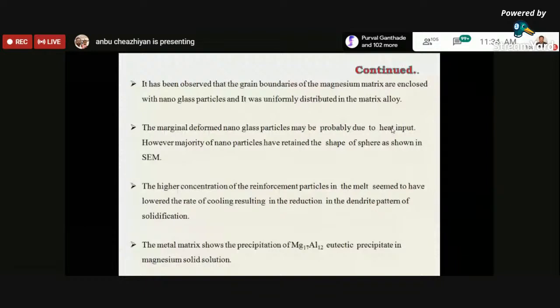It is also noted that a higher concentration of reinforcement particles in the melt seems to give a lower rate of cooling, resulting in a reduction in the dendrite pattern of solidification. Here we found precipitates of Mg17Al12 that are found along the grain boundaries of the magnesium solid solution.